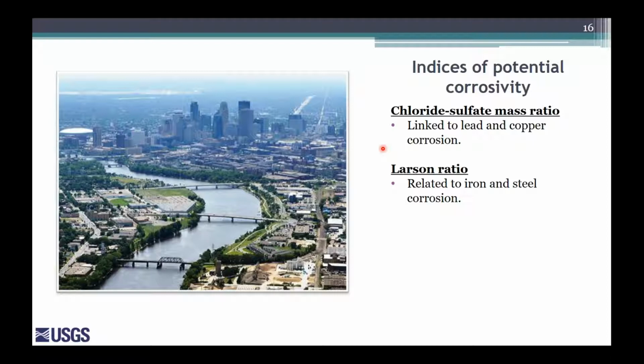The Larson ratio, on the other hand, expresses a potential for water to cause the corrosion of iron and steel. And so, as you can see, the trends in individual major ions, as well as their ratios, can be very important to determining the overall potential corrosivity of surface water and how it can affect drinking water quality.